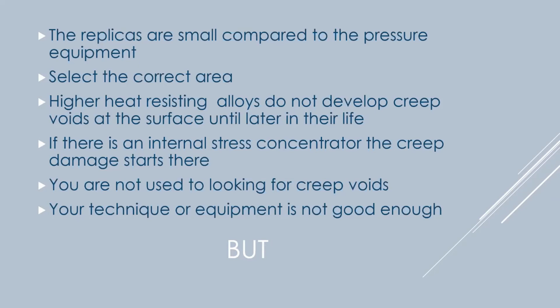And the other thing it doesn't work for is if you have a big welding defect inside your piping. It's a stress concentrator, and the creep damage will start on the inside before it will be detected on the outside. So we have to hope that there's nothing on the inside that gives us problems. The other problem is that you may not be used to looking at what voids look like, and that's always an issue. And your technique or your equipment maybe just isn't good enough.